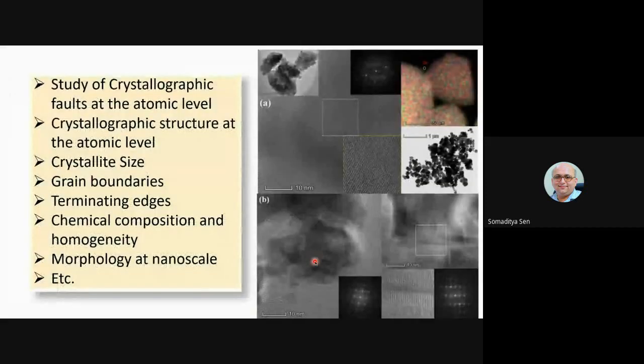So in our samples, let us show how zinc oxide also shows the same thing. From the FESEM, we found that the particles were about 50 to 100 nanometers in size. That is also seen in a normal TEM picture, where we can see the particle size.